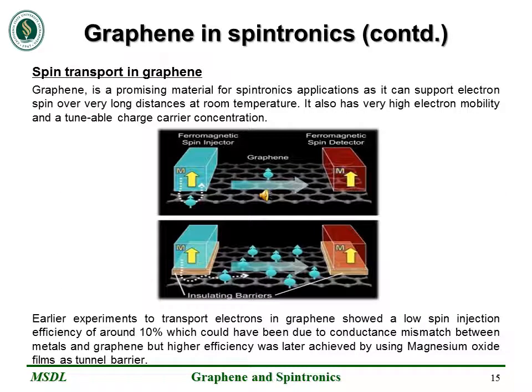Graphene is a promising material for spintronics applications as it can support electron spin over very long distances at room temperature. It also has very high electron mobility and a tunable charge carrier concentration. Earlier experiments to transport electrons in graphene showed a low spin injection efficiency of around 10%, which could have been due to conductance mismatch between metals and graphene. But later, higher efficiency was achieved by using magnesium oxide films as tunnel barriers.